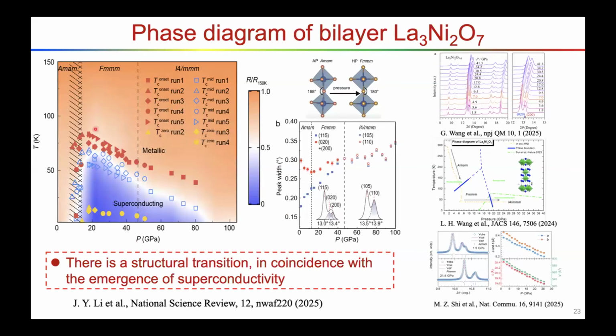So here is the phase diagram for the bilayer 327 compound under high pressure. There is a sharp enhancement of the superconductivity under high pressure. If we simply look at this phase diagram, we can see something must happen here. If we study the structure transition, at the beginning we claimed there's a structure transition from Amam to Fmmm. The difference is the angle along the c-axis, from 168 degrees to 180 degrees. But it's still orthorhombic.